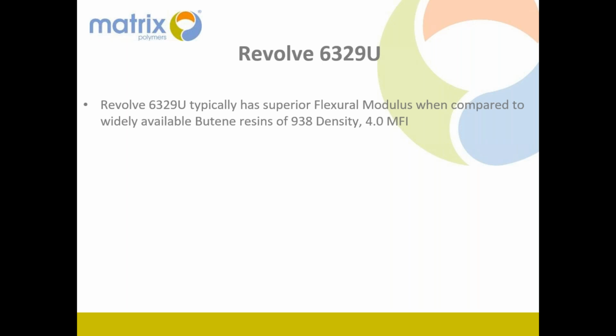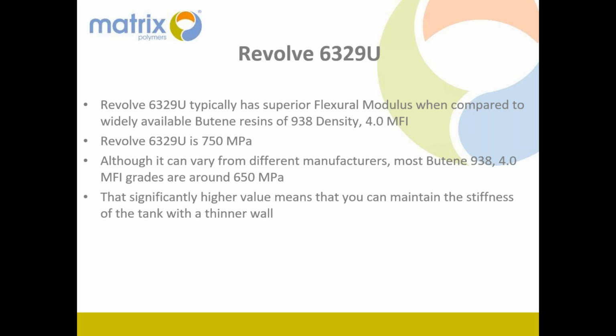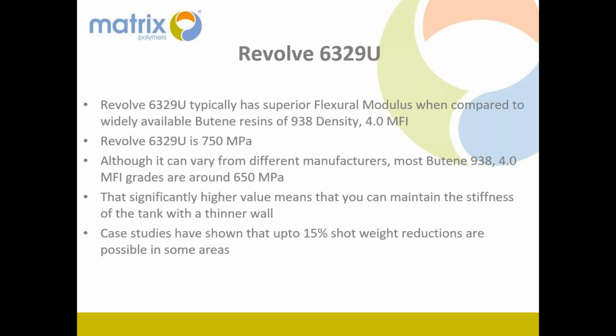So this is the material offered by Matrix. Revolve 6329U is a very popular material now, widely used in India, in the Middle East, and in other parts of Asia. We have case studies of up to 15% shot weight reduction without compromising on the features and performance of the part. In fact, probably making a better part than the same part made in a butene resin. This is an advantageous feature commercially also when using a hexene resin to make a better part.